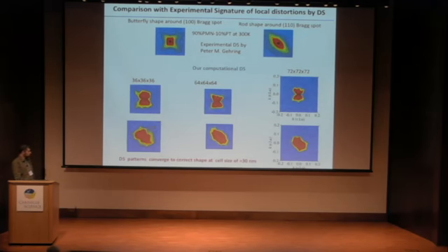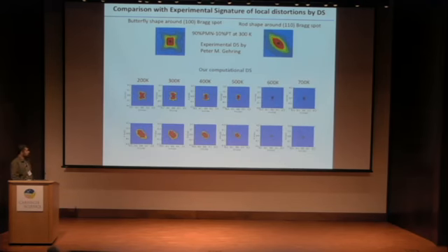So we can look at our computational diffuse scattering as a function of temperature. Here, again, in the ferroelectric phase, there is no diffuse scattering. You just have a Bragg spot over here, both in the 100 and 110 zones. And when we go to 500 Kelvin, we have the appearance of diffuse scattering. And then as we go down in temperature, it changes shape more or less, I think, at T star and at TF. And this is in agreement with the experiment.